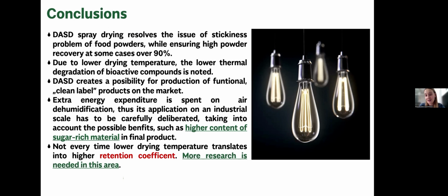To conclude this presentation and the research on dehumidified air-assisted spray drying, I would like to underline the most important thing that should be taken from it is that this technique resolves the issue of stickiness of food powders, and at the same time it ensures very high powder recovery, in some cases even over 90% powder recovery. Due to lowering the drying temperature, we observe lower thermal degradation of bioactive compounds, but this is not the same as retention coefficient. But what is really also very important, that due to lowering drying temperature, we can lower the carrier content and increase at the same time raw material in the powder. So we can increase the bioactive compounds potential in the final product, which would not be normally achieved using traditional spray drying. So that is very important.